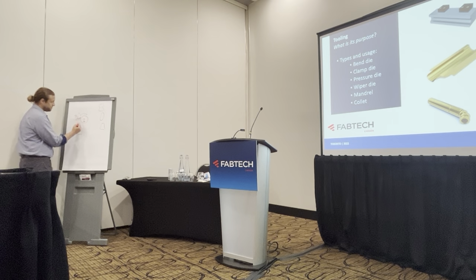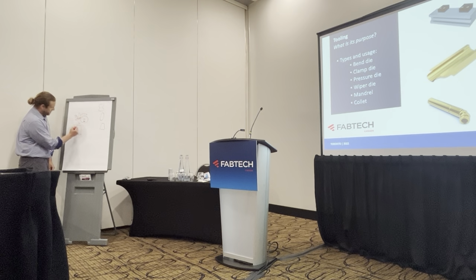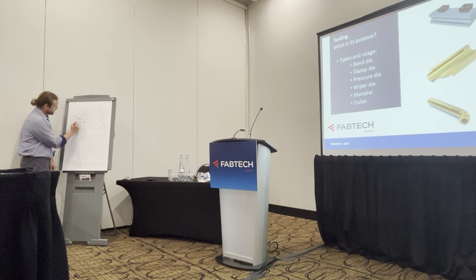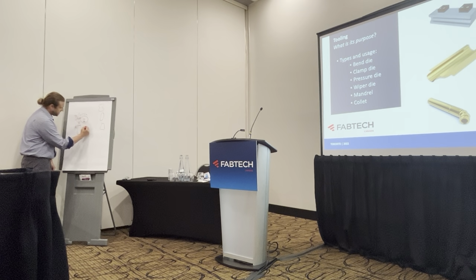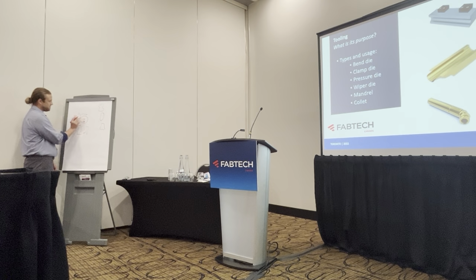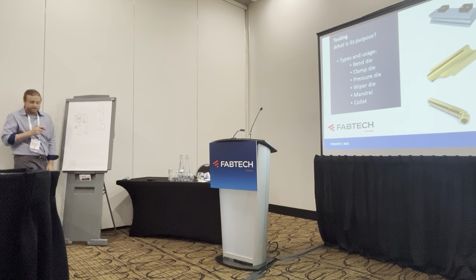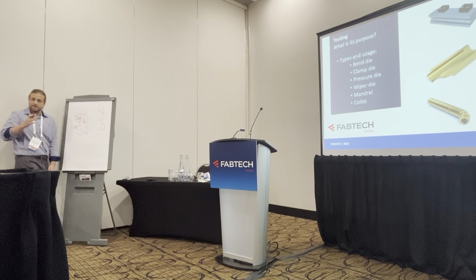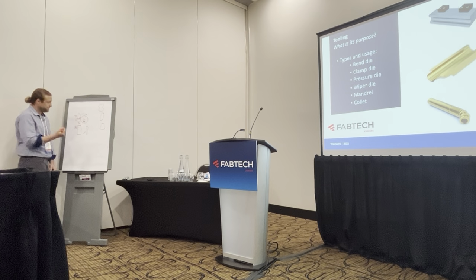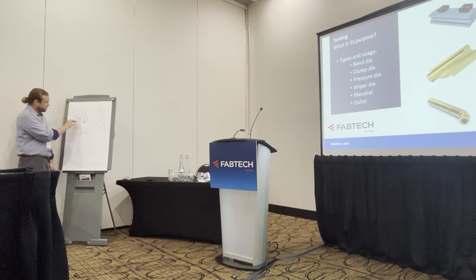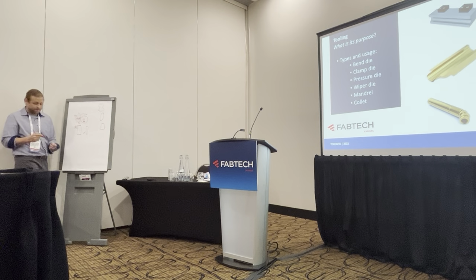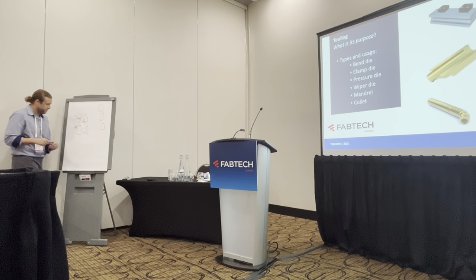Pressure die is what, well, sorry, it should be over here. Your pressure die comes in and pushes the tube, which keeps the tube linear and not wanting to kick out. What happens is, as the tube's forming around the bend die, the back side of the tube will want to kick out, causing bend issues. So this pressure die helps keep pushing the material linear and keeping the back side of the tube from kicking out, which can cause manufacturing issues.